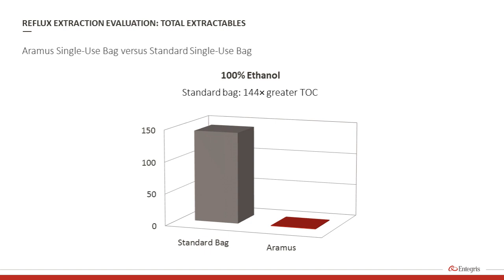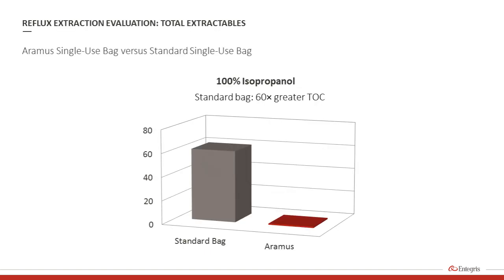The data on this graph shows a dramatic reduction in extractables when using a fluoropolymer. This data compares the Aramus film and a typical multi-layer polyethylene bag for extractables using an aggressive reflux extraction process using 100% ethanol. The data shown here shows that the multi-layer polyethylene bag had 144 times greater TOC than did the fluoropolymer film. In similar fashion, the extractable data shown here was generated using an aggressive IPA reflux extraction process. The results with IPA show that the multi-layer polyethylene bag had 60 times greater TOC than did the Aramus bag. This all results in a greater reduction in risk associated with extractables.